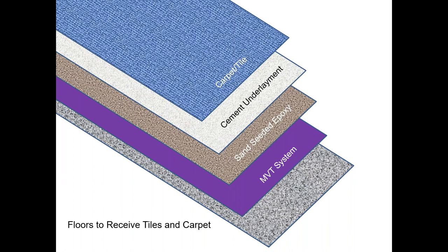If I'm going to actually be putting down something like carpet or tile or anything with an adhesive that typically bonds to concrete, the way I do that is I put down the moisture vapor transmission system, and then I put down an epoxy primer with this that's sand seeded, which I'll show you in a second. And then I follow that with a cement underlayment, usually, let's say a quarter inch to a half inch of cement underlayment. And now I've got a cementitious surface without moisture vapor drive coming up through it that the carpet and tile adhesive is designed to bond to.